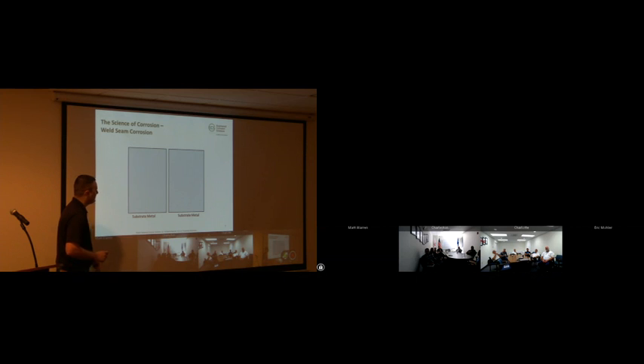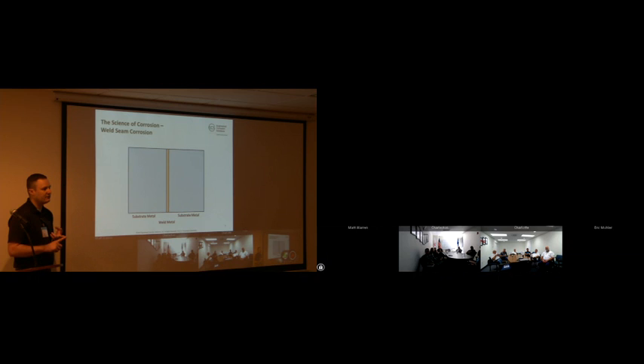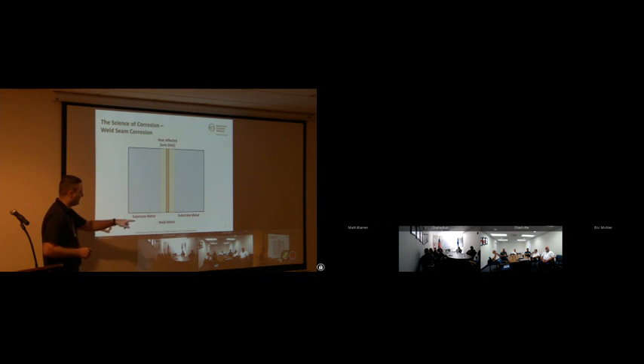So let's talk a little bit more about weld seam corrosion. This is just a visual on it. When you weld two pieces of metal together, you have to be cognizant of two things. The heat affected zone is one of them, but you also have to make sure that the weld metal you're using is compatible. Obviously the weld metal that we use when we fab pipe is compatible. The thing we have to worry about is the heat affected zone, which is illustrated here.